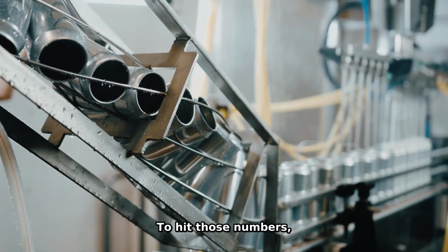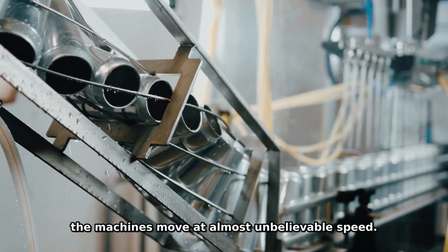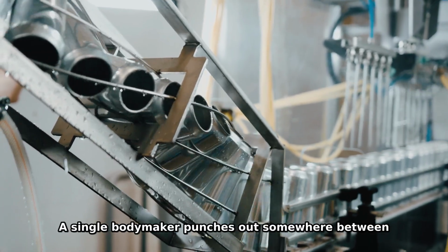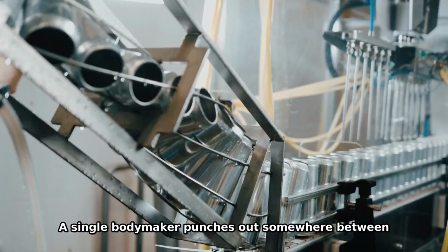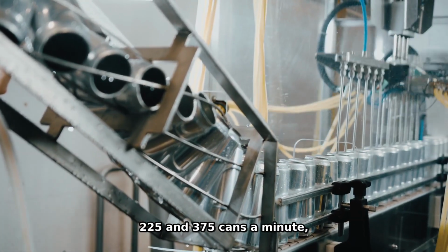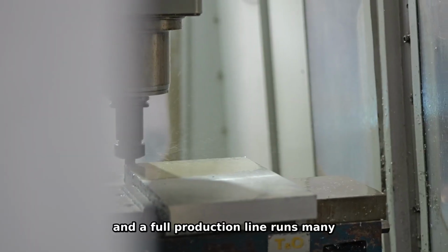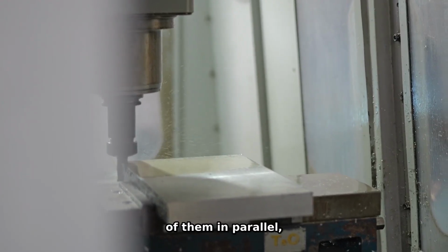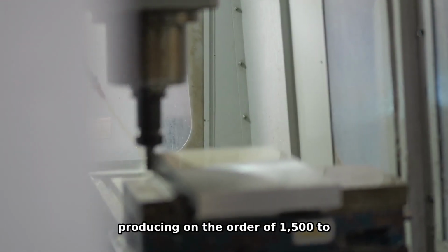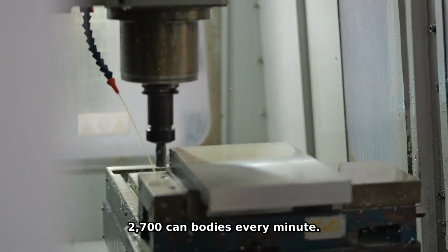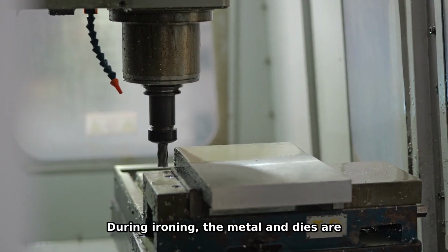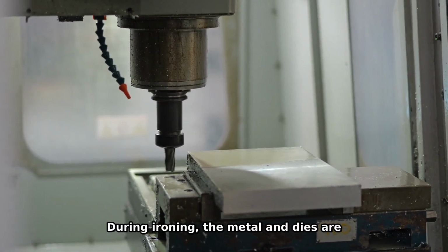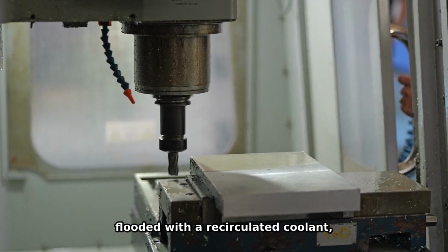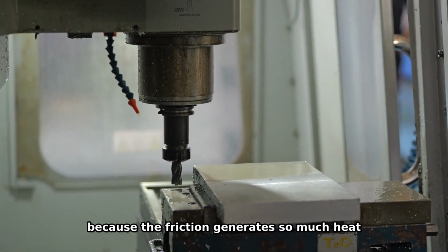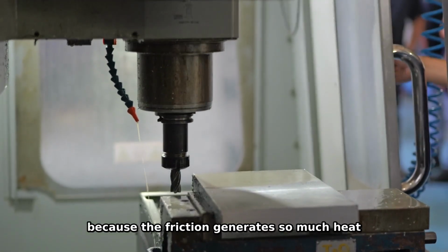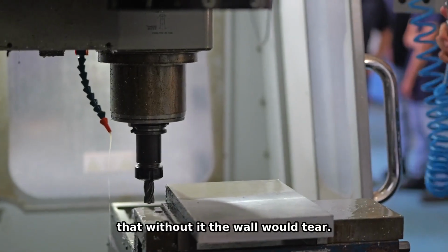To hit those numbers, the machines move at almost unbelievable speed. A single body maker punches out somewhere between 225 and 375 cans a minute, and a full production line runs many of them in parallel, producing on the order of 2,700 can bodies every minute. During ironing, the metal and dies are flooded with a recirculated coolant because the friction generates so much heat that without it, the wall would tear.